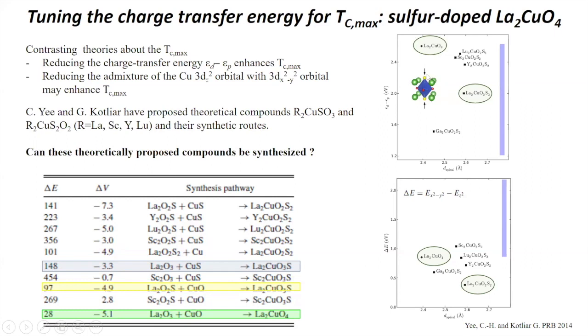These are the apical oxygens, and there are two compounds that would be formed if you had one or two of those oxygens replaced with sulfur. And this presumably would reduce the charge transfer energy, and that would lead to an enhancement in TC. So an interesting thing about this paper was that it actually predicted certain synthesis pathways that we could follow. And so in fact, we took that challenge and tried to synthesize the lanthanum cuprate with sulfur on one or two apical oxygens.